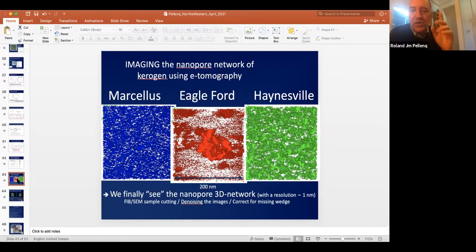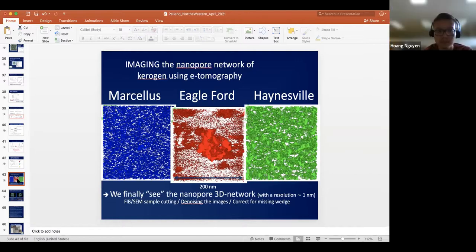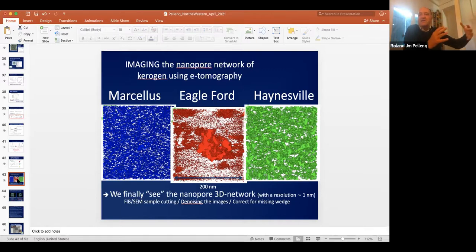No. It's actually more. Okay, you have to define the thing. It's a matter of what you define, because this is me being a methane molecule when I start touching the carbon nearby, right? So you need to add on both sides a carbon size, which is 3 angstrom. So the bottom is the methane molecule plus 3 angstrom, which is around 6-7 angstrom. Correct? Yeah, that makes more sense, because of course 1 angstrom is smaller than C-C. This really matters as a size, right?